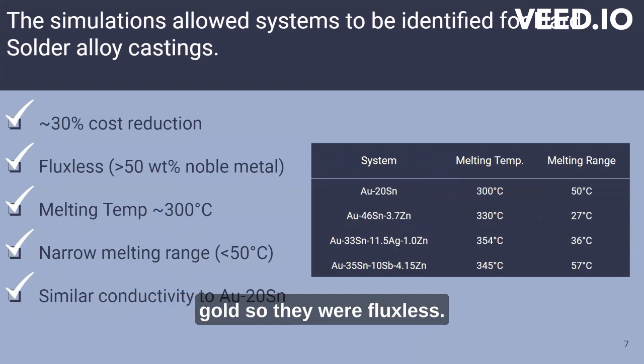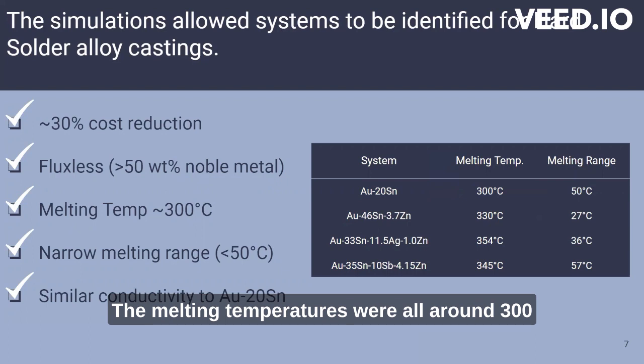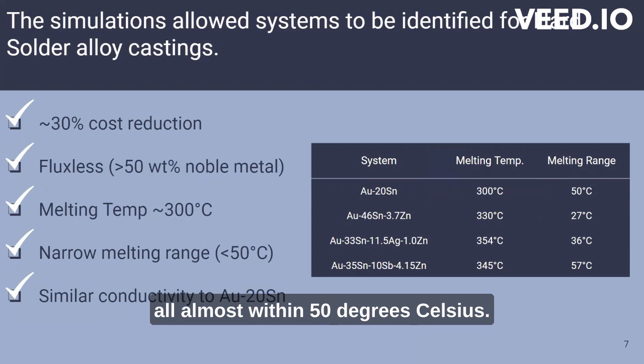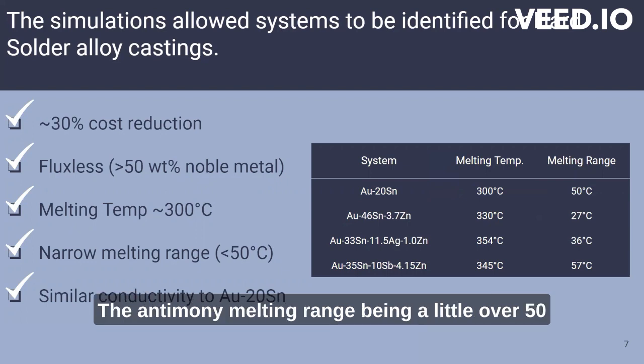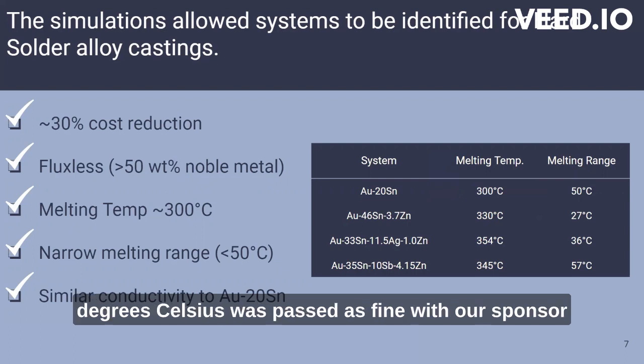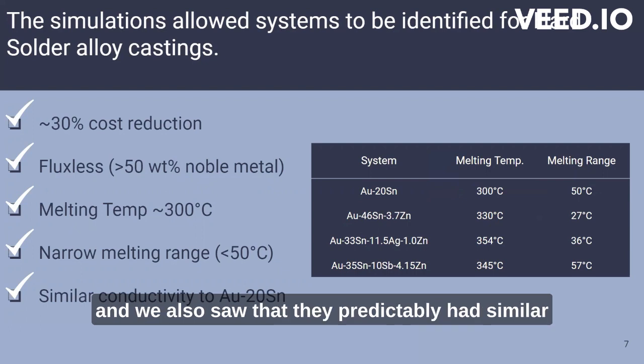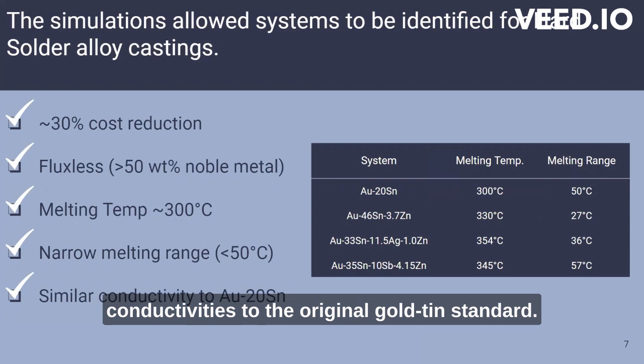So they were fluxless. The melting temperatures were all around 300 degrees Celsius, and the melting ranges were all almost within 50 degrees Celsius. The antimony melting range being a little over 50 degrees Celsius was passed as fine with our sponsor. And we also saw that they predictably had similar conductivities to the original gold tin standard.